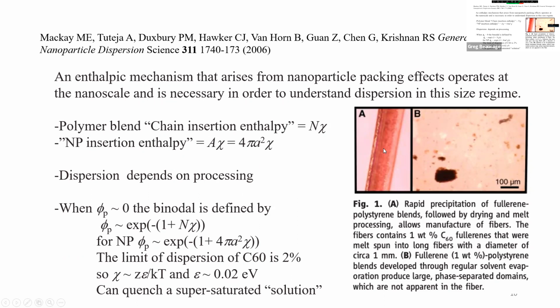And he says because he can only get this to mix up to 2%, that's his binodal number under whatever condition he made it. So he can get a chi parameter. From the chi parameter he gets, he can get the energy of interaction between the particles and the polymer. And this is a really small number. It's 0.02 electron volts per nanoparticle, small.